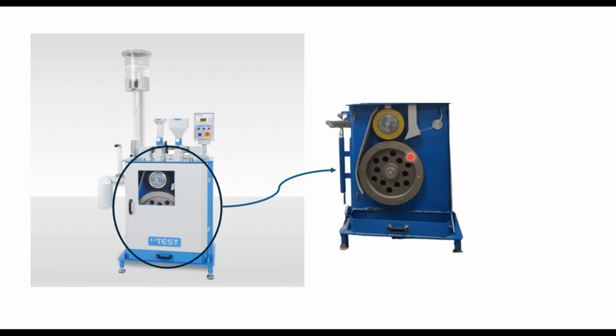Then you have a small rubber tire wheel here of 20 centimeter diameter, and the width of the periphery of this wheel is 5 centimeter. It has a loading mechanism here to apply a load of 40 kg on the stone surface. When they are in contact, this wheel will create a load of 40 kg on the surface of the road. Then you have a motor inside this machine to rotate the road wheel about its own axis at a speed of 320 to 325 revolutions per minute.